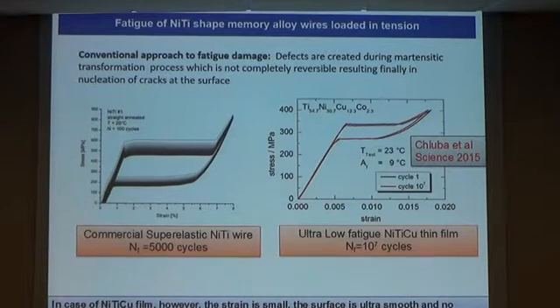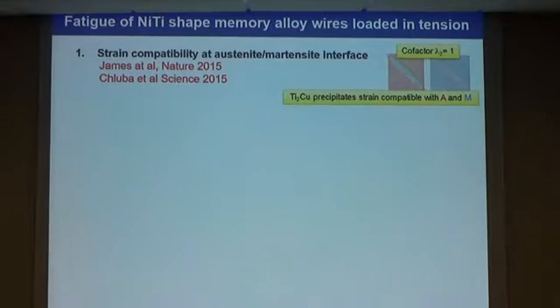If you have a slightly different composition with titanium rich, it looks like they measured 10 to 7 cycles without any change of functional behavior and without any fracture. But if you put the same figure, which looks very nice here, into the same frame, you see it's below 1%, so in fact it's kind of limited. But still there is a chance and there is where to go.